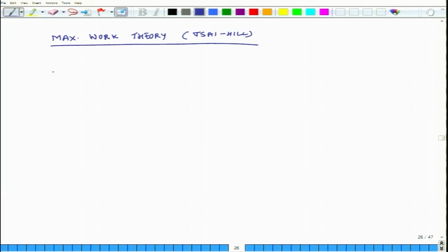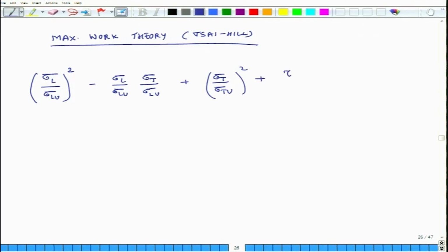So, what does the result say? It says that the system is going to fail if the right hand side of this equation exceeds 1. If it does not exceed 1, then it will not fail. So, what is this? Sigma L divided by sigma Lu, squared, minus sigma L divided by sigma Lu times sigma T, and remember here the denominator is still sigma Lu, not Tu, I am sorry, it is sigma Lu, plus sigma T divided by sigma Tu, whole squared, plus tau Lt divided by tau Ltu, whole squared, should be less than 1 for no failure.